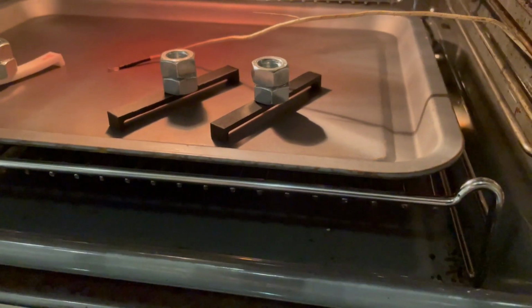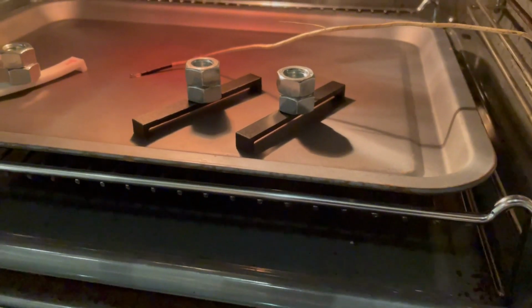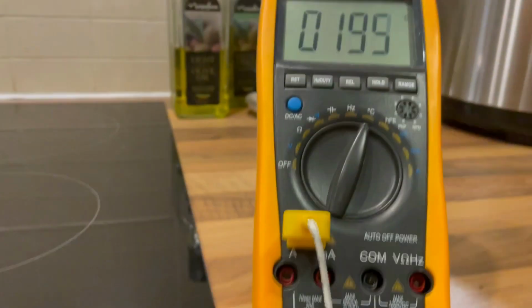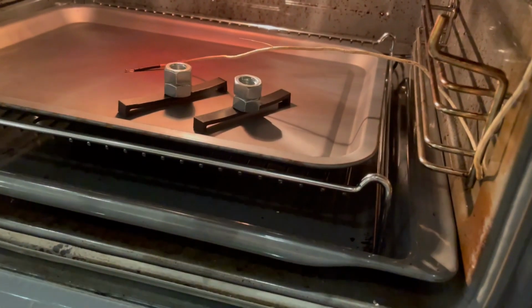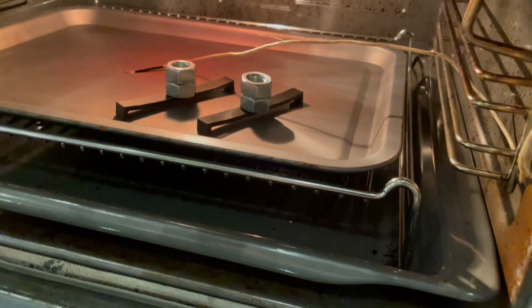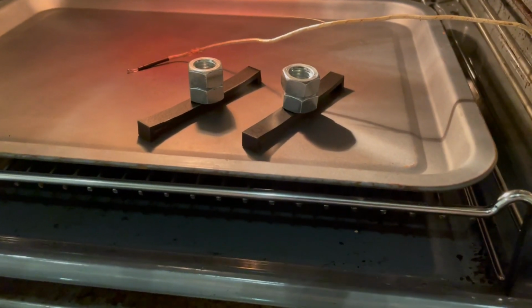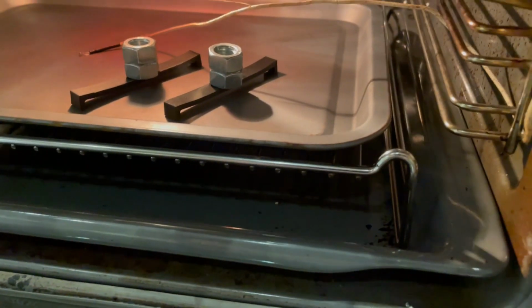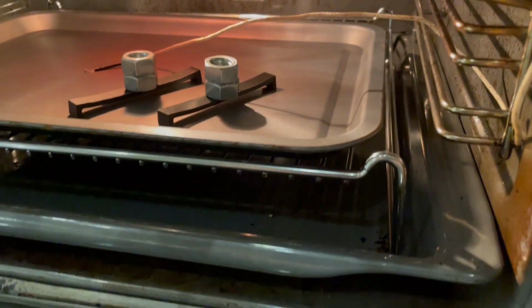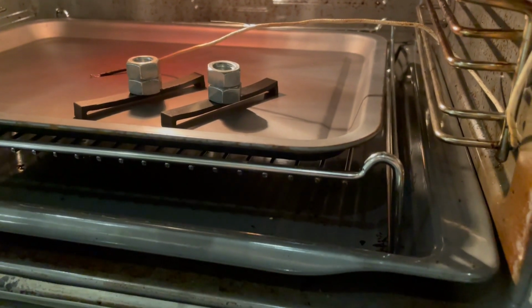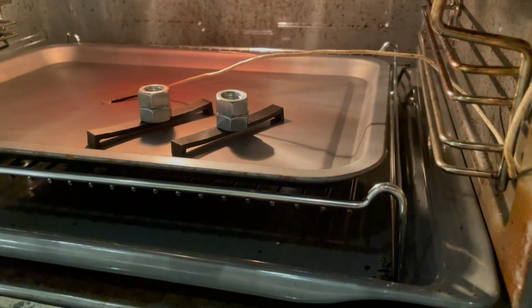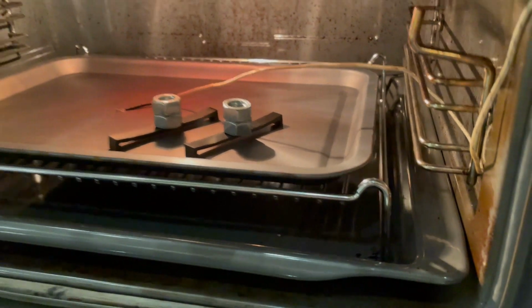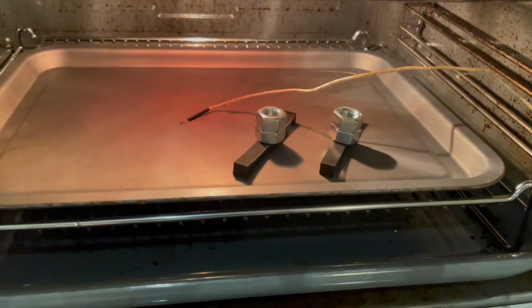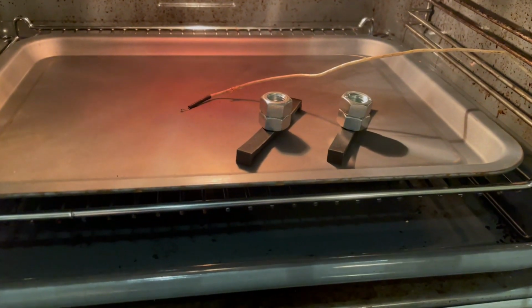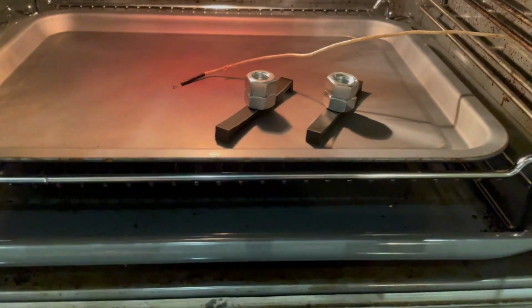However, the 2 nylons are absolutely straight as a die. So it's 195 degrees and both are showing signs. The first anneal, the lower temperature anneal, has completely gone, but the second annealed temperature, the longer annealed item, is just starting to sag. So maybe 3 or 4 degrees in it, not much.